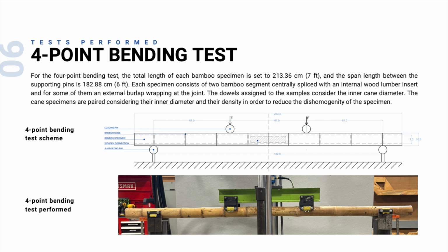And in parallel, we also performed 4-point bending tests. And here each specimen was 7 feet long with 2 bamboo segments spliced together using a dowel in the middle. And some joints also had the burlap wrap, while some others did not, so we could compare their behavior. And the canes were paired according to their diameter and density. This was made to reduce the variability as much as possible. So here the main questions were, does the burlap wrap improve the strength of the system, and how does the dowel size again influence the bending resistance?